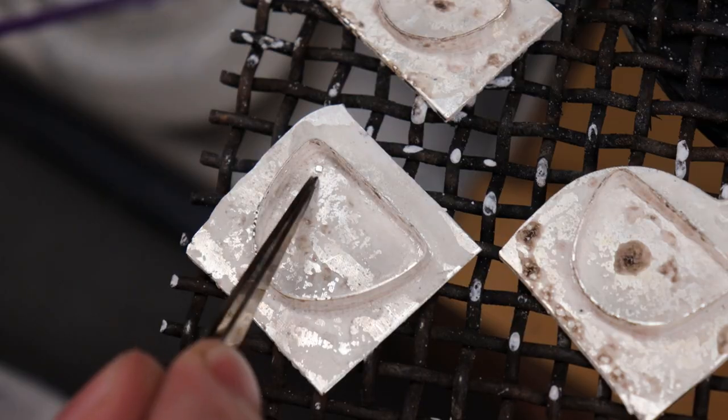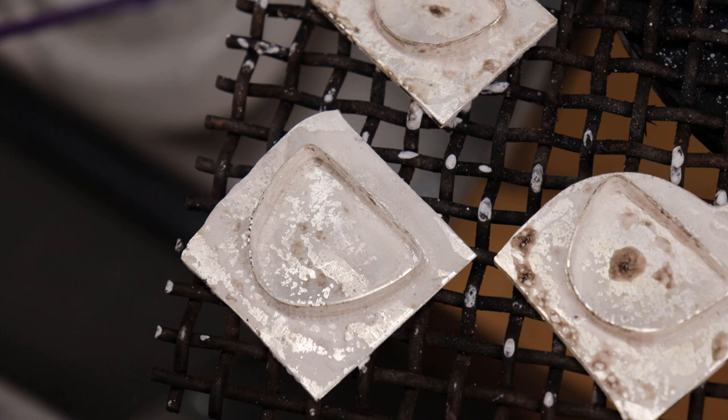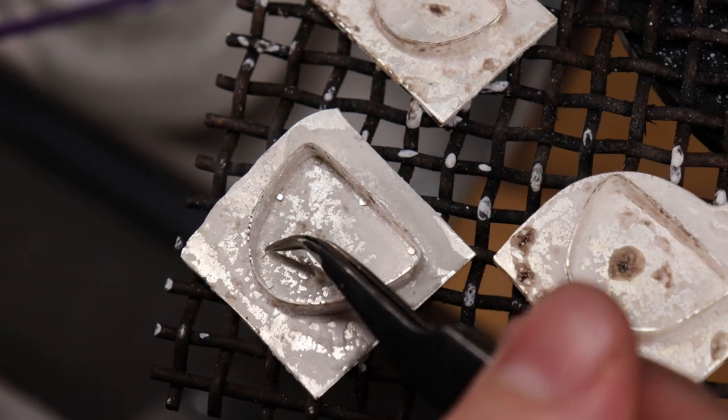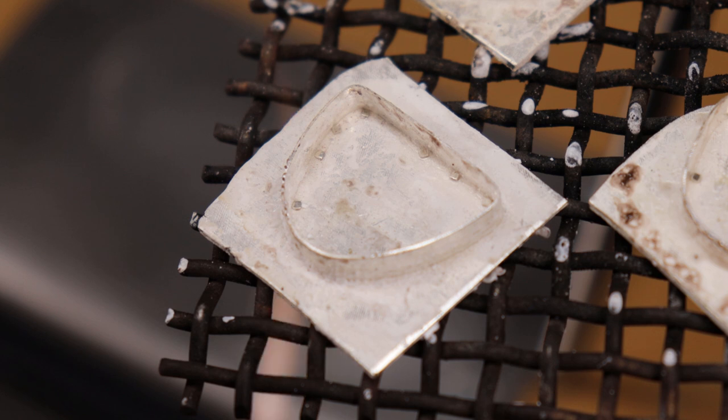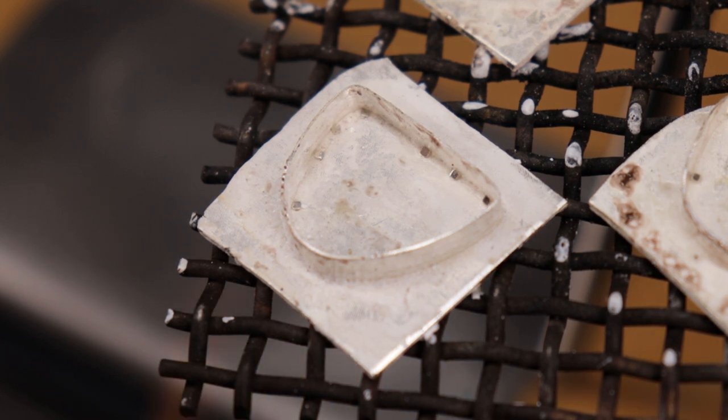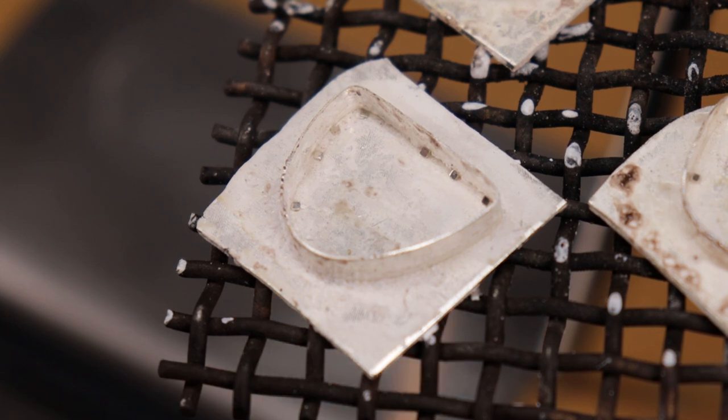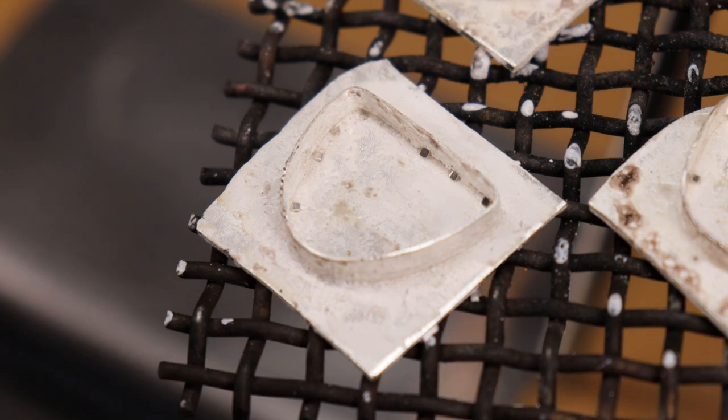I'm going to use medium solder for this, and I'm going to place it touching the wall of the bezel and the base plate floor. So when it comes to heating, I actually heat them from underneath, and I make sure to use a heavy gauge mesh screen to do this. And if you use a thinner gauge, you usually melt the screen before you'll actually solder anything.